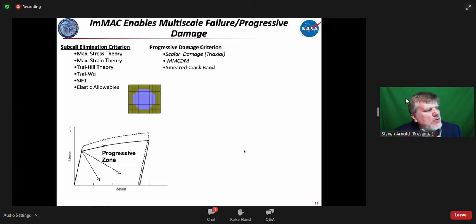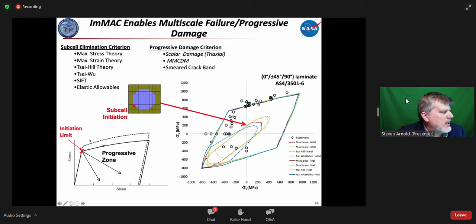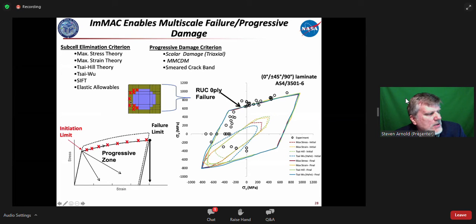And now moving on, those were more initiation surfaces, obviously. Now, like here, we can have initiation, but we can also move beyond that and allow progressive damage to take place, where we allow each subcell to continue to damage, and then the accumulation of that damage ultimately results in, let's say here, the zero-ply failure of a quasi-isotropic laminate. One of the interesting things, as you kind of saw from the previous slide, there is a difference between failure theories when we're speaking about initiation, but when we get to the final failure and you've had propagation go on, the significance of the failure theory selected diminishes significantly.